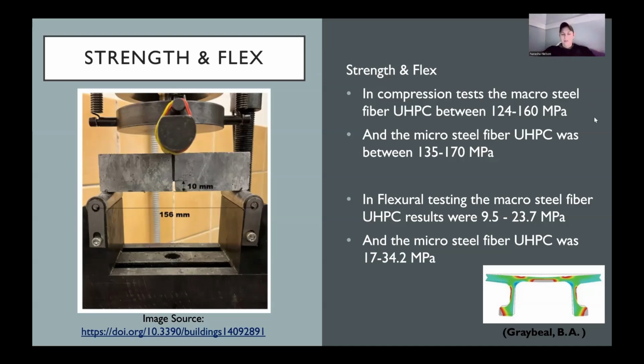The other thing was the flex test. This photo over here is a picture of their actual setup for the flex test. The flex test with the macro steel fibers was between 9.5 and 23.7 MPa before failure for the ultra high performance concrete. And for the micro steel fibers in the ultra high performance concrete, it was 17 to 34.2 MPa before failure, which is unbelievable and pretty amazing. That's really awesome, really cool characteristics that ultra high performance concrete does have.